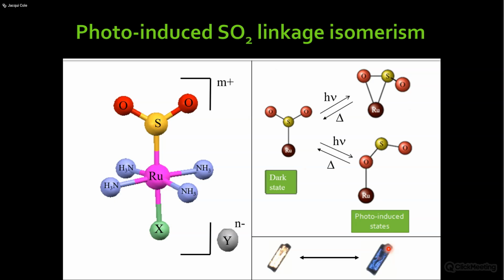you many examples. And so in terms of the photo action, what is happening is that you have this sulfur dioxide ligand bound in the dark state between the sulfur and the ruthenium. But what happens when you cool these single crystals down? So this all happens in the single crystal state. Everything I'm showing you throughout the presentation will be in a single crystal. And when you apply green light generally and keep it cold, let's say 100 Kelvin, that type of cold, then you fire light at it and it will convert into one of these two photoisomers.